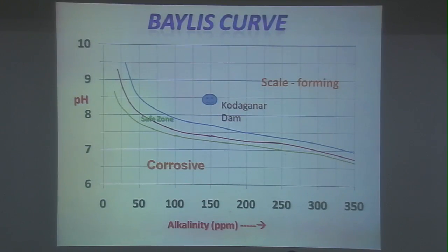You can see that the tested value of the Kodaganar Dam is falling above the safe band. This is the safe band. If the values fall within this band, then the water will be very, very safe. Actually, the values of the Kodaganar Dam are falling above the safe band. It means that the dam has scale-forming water. That's the reason why the shutters have become more thick. They have found some problems in the operation of shutters.